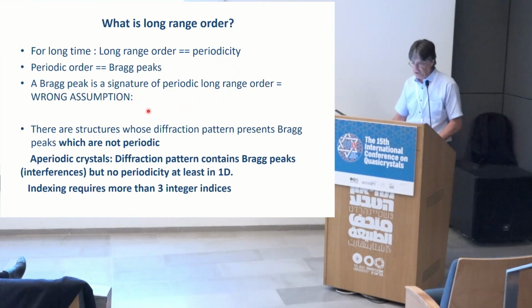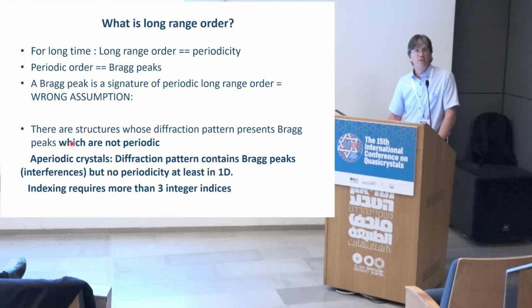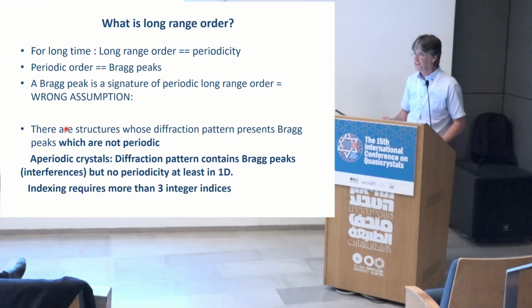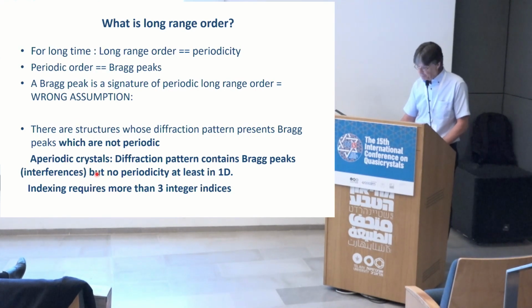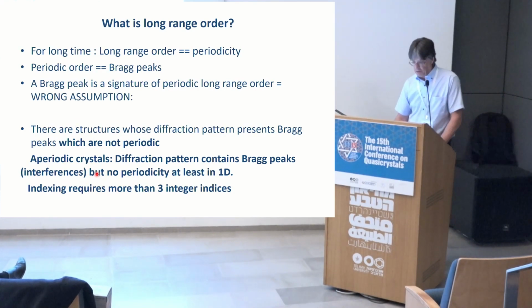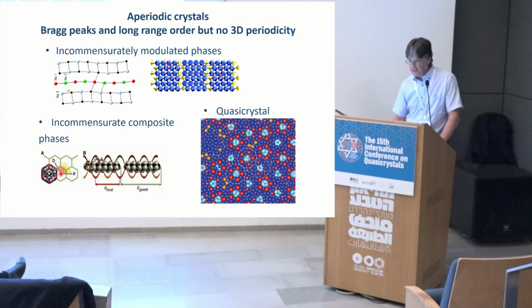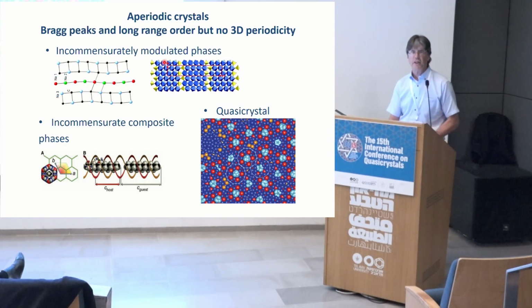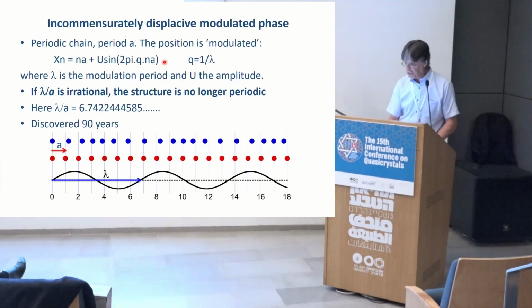You can have structures which are not periodic, but still will give rise to Bragg peaks. The most famous are quasicrystals, discovered by Dan Shechtman, but I will show you first an example in an aperiodic crystal where you have a modulation, and the indexing of the diffraction pattern requires more than three integer indices. So again, these are the three families, and I will just concentrate briefly on this family here to explain how we can have long-range order without any periodicity.